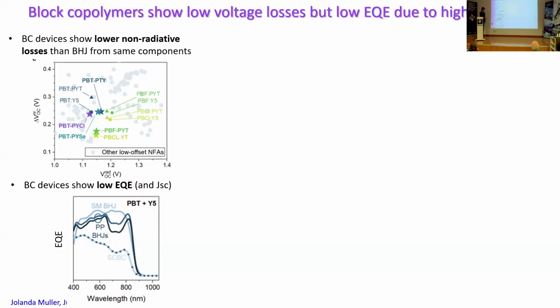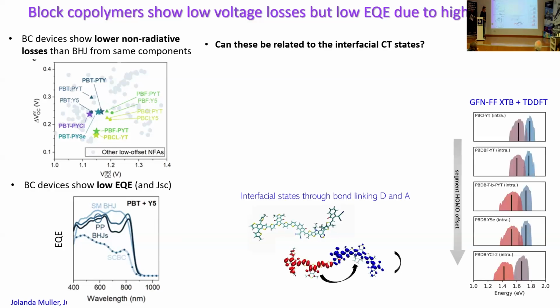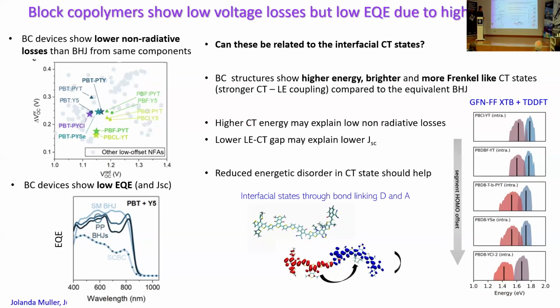And then to try to understand what could be leading to that from a molecular level, we did some calculations on the nature of these interfacial states that would be formed between the donor and the acceptor. And we were looking at different components that would produce different offset arrangements. But what we can see is if we compare a combination of materials in the block copolymer structure compared to a bulk heterojunction structure, the interfacial, the through-bond excited state tends to be larger in energy, and